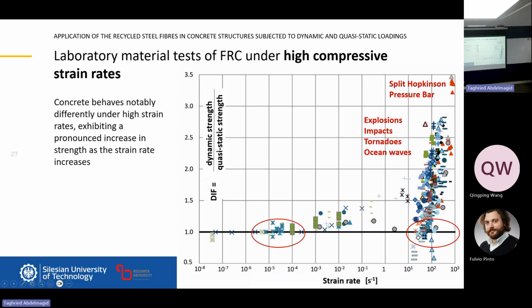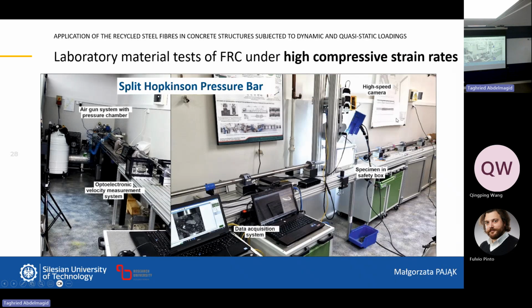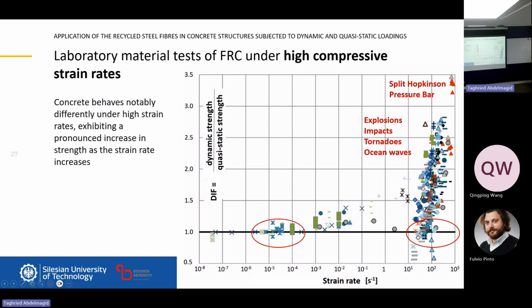Yes, so the military is using fiber reinforced concrete everywhere, because it is obvious that when you have plain concrete, it just splits because it's brittle. When you have fiber reinforced concrete, it can catch all the energy. The test that is used is the split Hopkinson pressure bar. And one more very important thing: in the test, comparing the quasi-static compressive strength with the strength under high strain rates, you can see even 2 times, even 3 times the quasi-static strength. Yes, so it's much higher.